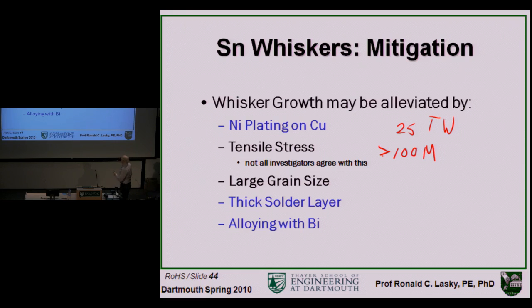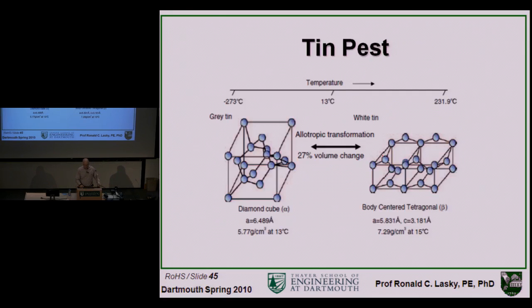There are all sorts of conferences on tin whiskers, and again, I'm not saying it's a legitimate concern for very high reliability, mission critical products, but typically it takes months for the tin whiskers to grow, and before I'm going to worry about tin whiskers on this, I'm either going to drop it and it's going to have a problem, or we're going to want a newer one. So, but it is probably the thing that material scientists study in lead-free solder that is still contentious, and they have conferences on and so forth.